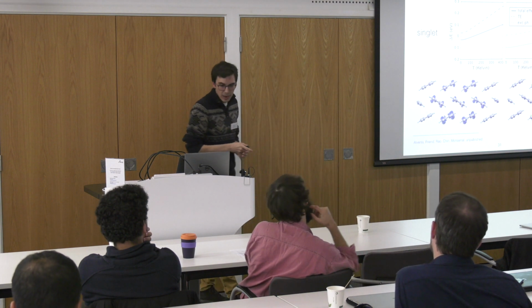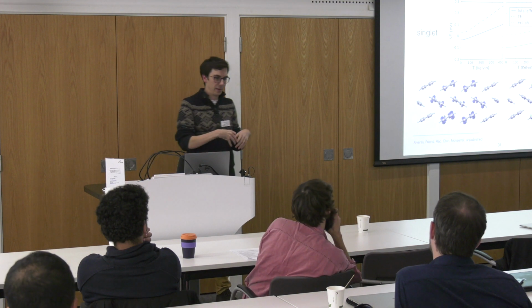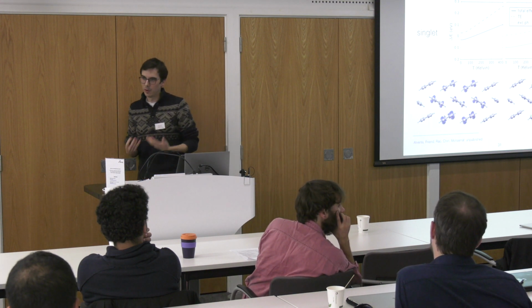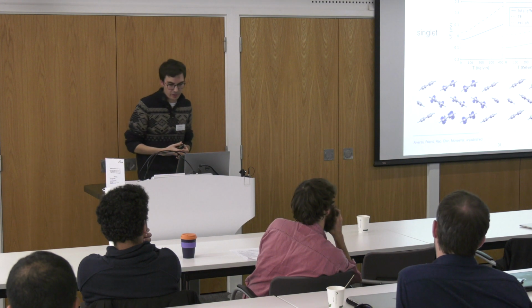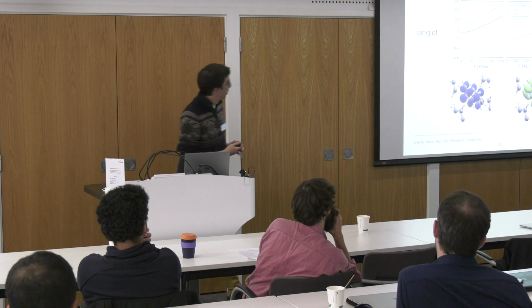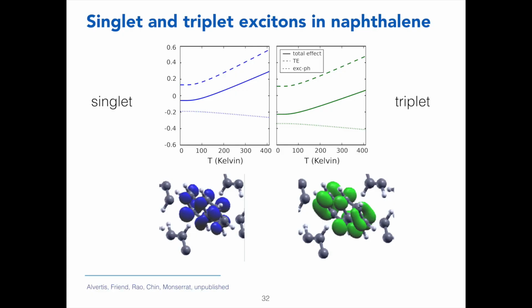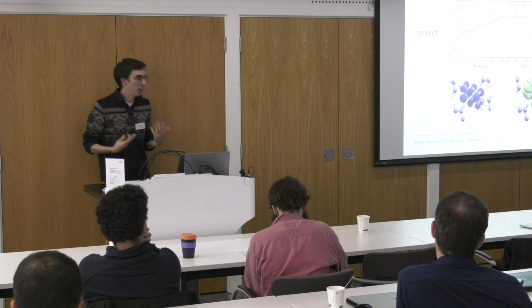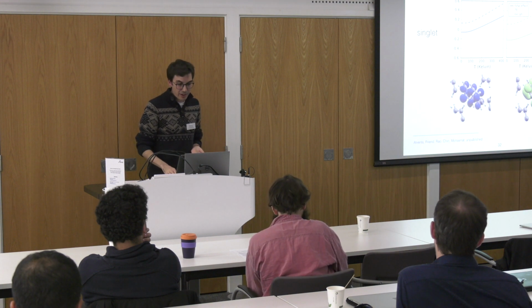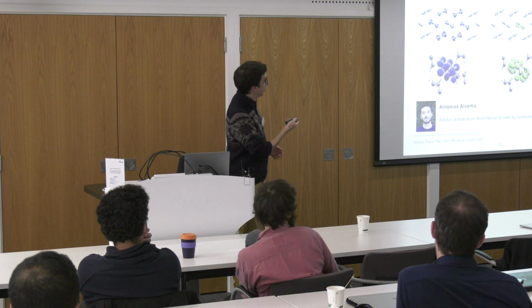So that was the hypothesis of how we have an interplay between the localization properties of these exciton wave functions and the dynamics of the system. And to confirm this, we looked at another member of the acene series, naphthalene, which happens to have both singlet and triplet excitons that are very much localized around a single molecule. And indeed, in this case, we find that the temperature dependence arising from exciton-phonon coupling in both cases is very, very similar, in line with their localization properties. So this is actually a very interesting story, and we've extended these results to all the acenes.